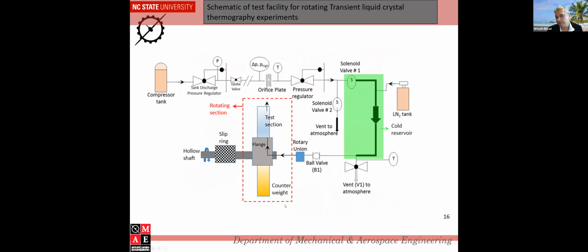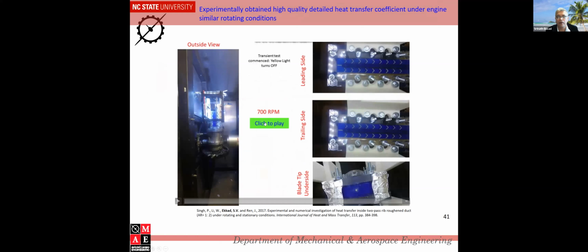In the rotating rig, what we do is we actually coat the surface. It's a plastic rig, not a plexiglass rig. We coat it with liquid crystals, thermochromic liquid crystals, which change color based on temperature. That is what I did my PhD on in those days. And then what we do is we coat and then take images of the color changes during the experiment, download the images, convert the images back to temperature, and then calculate the heat transfer coefficient. So just to give you an idea how an experiment looks.